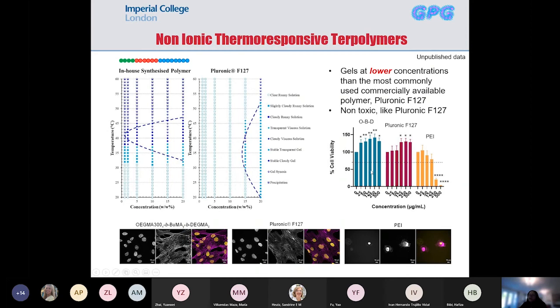In terms of toxicity, our gels at lower concentrations are, as expected, not toxic. It doesn't have any charges. If you compare it to a charged polymer like polyethylenimine that we know is toxic at higher concentrations, you can see that polyethylenimine has low cell viability when you increase the concentration, while our polymer and the Pluronic are both fine. And these are some images of the cells that show that they're healthy with the Pluronic and our polymer.